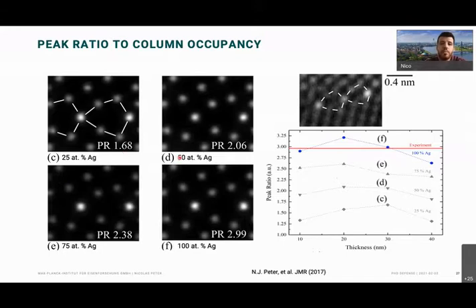How can we relate the peak ratio with the occupancy? Well, we do image simulation, quite a lot of image simulations where we have our MD cell or an XYZ file where we build the grain boundary based on our experiment. And then in these CSL points that I explained before, we put in silver to 25%, 50%, 75%, and 100%, which is a full column. And then we look at the peak ratio, and we see that they have certain curves.